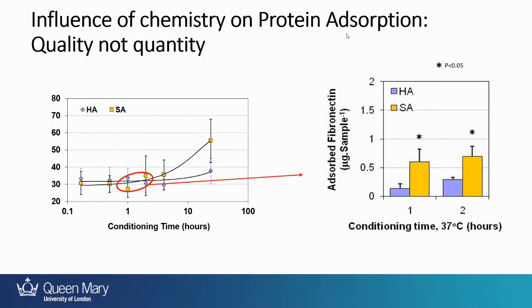So what we did then was look at what sort of proteins were being absorbed on the different materials, and found that if we took these two time points, where you've got no significant difference in the amount of protein on the materials, and looked at what was there, there were significant differences in the types of proteins. And the key one that was interesting was fibronectin, a protein that's critical to cell attachment. So the fibronectin was absorbing at much greater concentrations on the surfaces of the materials that were substituted with silicon. So the changes in the hydrophobicity and the surface charge of the material were resulting in more fibronectin absorption, which is then enhancing cell attachment.